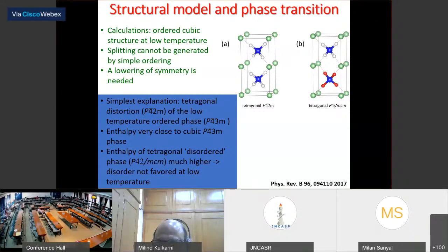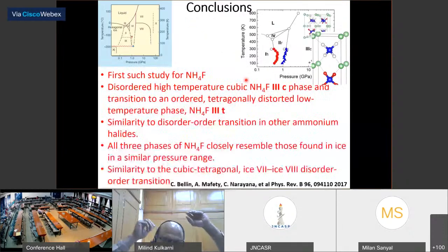But if you introduce a disorder into this, then you can see that the enthalpy is higher. So that means at a low temperature, it is actually not cubic, it is actually tetragonal. So what is exactly happening now?